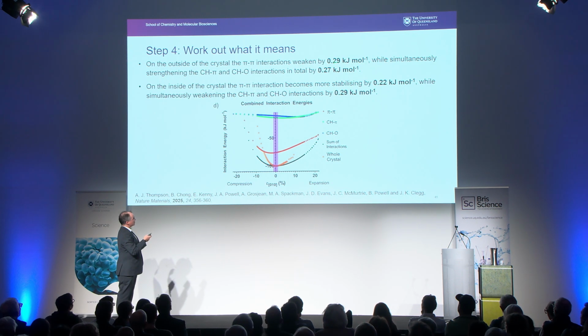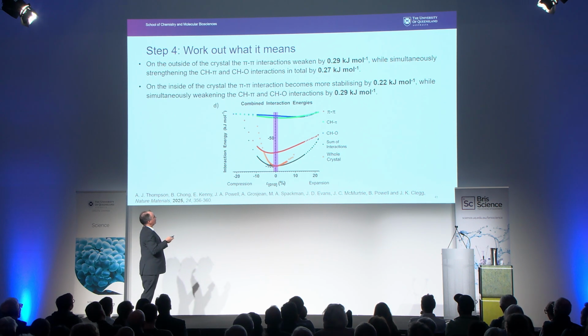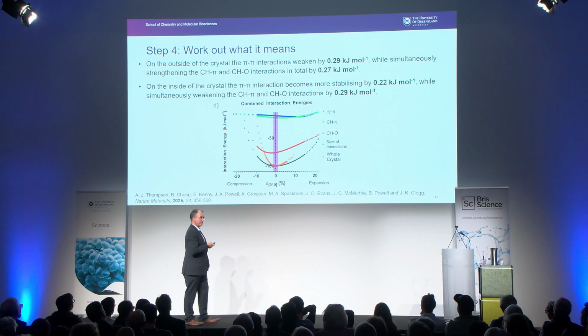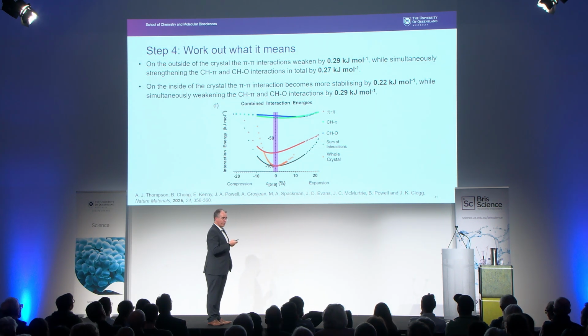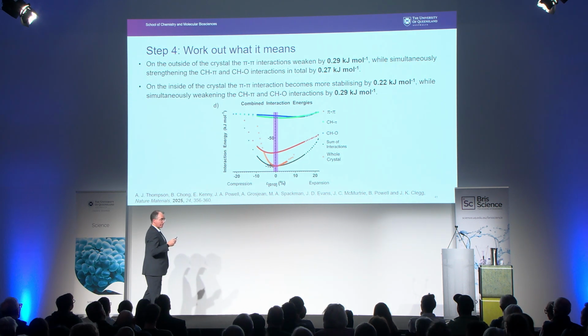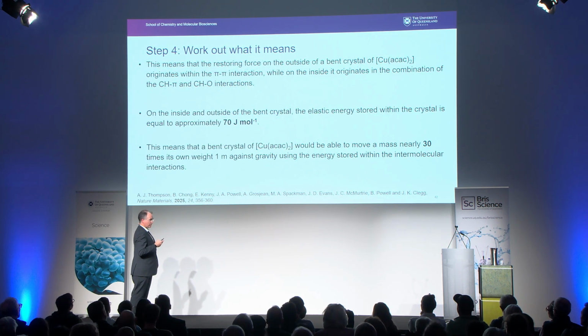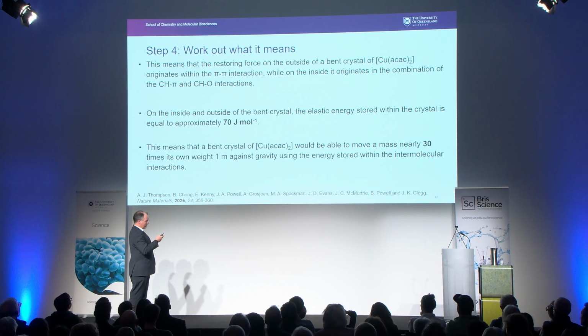And so when you integrate all of these out, you work out that the pi-pi interactions weaken by not very much, 0.29 kilojoules per mole, while these ones here strengthen by 0.27. And the opposite roughly occurs on the inside. So this isn't a lot of energy when you look at decimal places like this. But when you start to think about how much energy that really is, things become significant. So it means that we're storing about 70 joules per mole on the inside and the outside of a